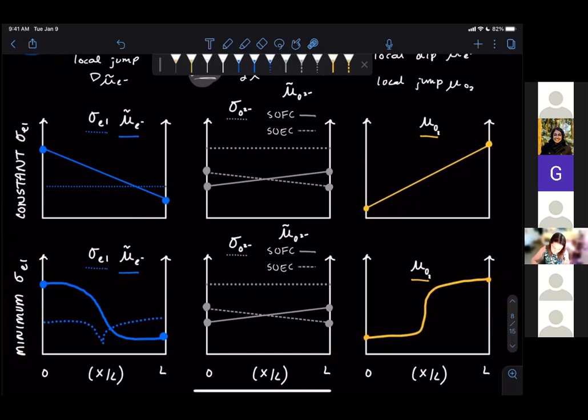And so the idea is if you've got more of a region within your solid electrolyte that's actually very close to these potential barriers, and if there's any more anomalies that might occur, there's potential that your neutral species chemical potential could dip or could jump to a point that you're starting to produce this neutral oxygen within the solid electrolyte or voids. And these are actually things that are observed. So let's take it that step further and add that anomaly and see if that will produce what we expect, which might be a jump in chemical potential of oxygen, and thereby some sort of degradation reaction in our solid electrolyte that we do not want just because of a transport property.